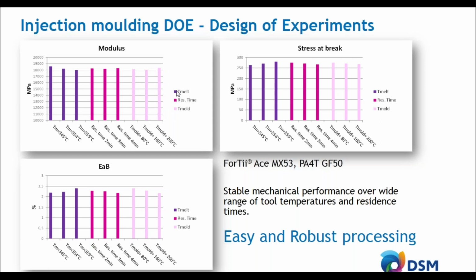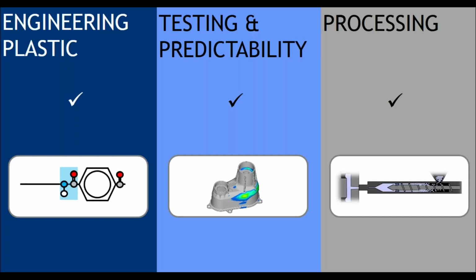And what you typically see is that within the operating window, with the melt residence time up to 4 minutes, a mold temperature from 80 degrees up to 200 degrees C, there is very limited variation in the stiffness of the material, the strength, and also the elongation at break. So the materials in our portfolio for metal replacement are very stable in processing, and that's also the feedback that we get from our customers, like for example VDL. So we have covered now a few very important topics in the field of going from a metal to an engineering plastic, how to deal with the prediction during lifetime and also with processing.